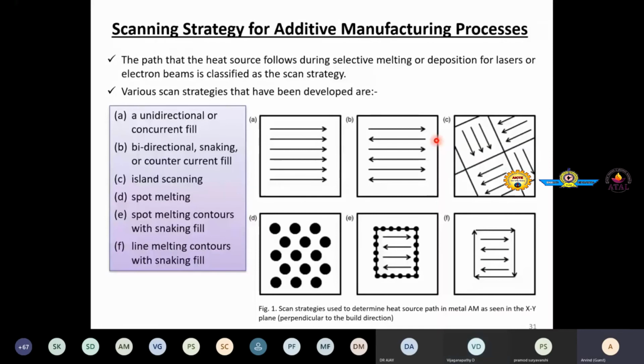Now, I would like to introduce you to scanning strategy. I told you something in the previous slides, but you can see various scanning strategies are possible. For example, A is unidirectional, B is bidirectional, C is island scanning, D is spot melting, E is spot melting contours with snaking fill, F is line melting contours with snaking fill. So you see, these are important so that the microstructure anisotropy and residual stresses can be controlled, right?